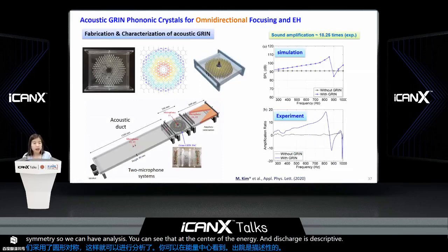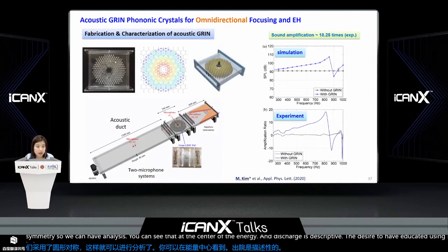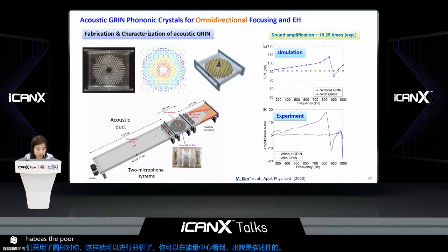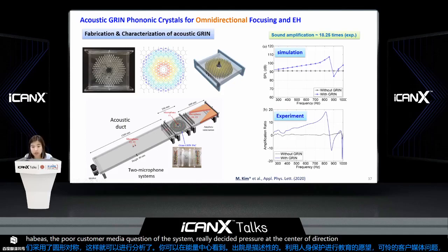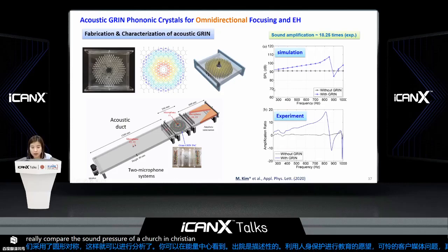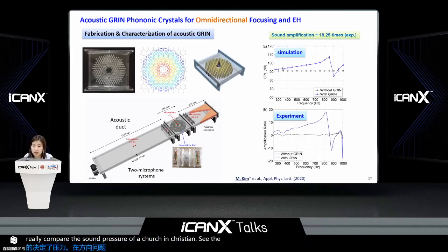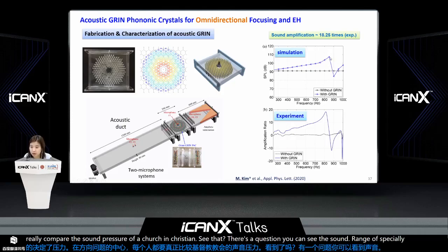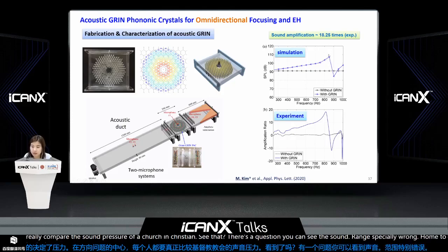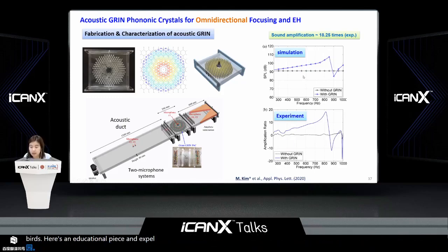The design we have, we fabricated using ABS like before, and we custom made the acoustic duct system to evaluate the sound pressure at the center of the GRIN phononic crystals and without it too. When we compare the sound pressure of the GRIN phononic crystals with nothing, you can see that there's amplified sound pressure. The sound is amplified within a wide range of frequencies, especially around 800 hertz, where maximum amplification occurs. In experiment, the same thing can be observed.